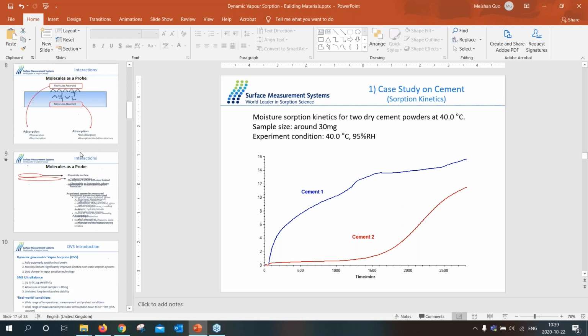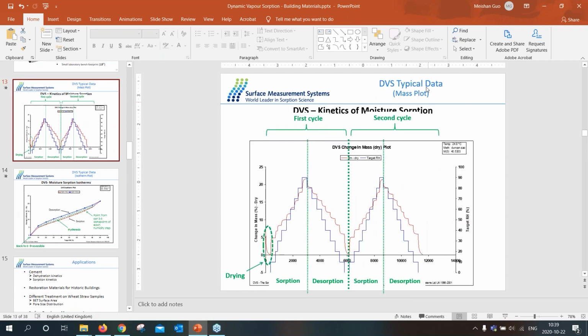Well, do you mean in case of those kinds of experiments, we do water vapor from 0 to 90% RH. At each step, it will wait for equilibrium, reaching a steady state, and then the system will detect the change of the mass, and when it reaches equilibrium, it will jump to the next stage automatically. So we can ensure each stage is reaching a perfect equilibrium. But if some samples take too long to reach the equilibrium, like at very high RH here, it will just jump to the next stage after a maximum time. We can do all the settings within the software by selecting different times for the step or selecting different criteria for the equilibrium.